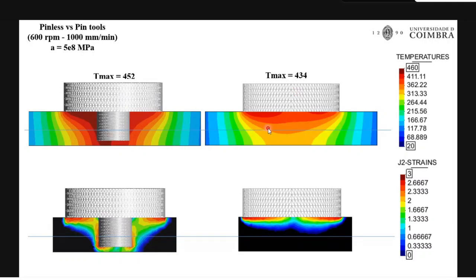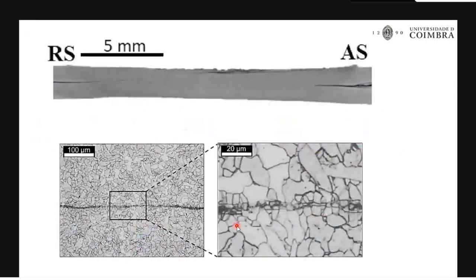Here you can find two results, the temperature and the strain. As I explained before, the advancing side has the higher temperature, and the temperature distribution is highly limited to the top region of the material, where lower temperature is shown here. When you look at the strain, you have a lot of strain in the outer boundary, because the angular velocity is higher in the outer region with respect to the distance. So you have the higher strain and higher temperature there. And here you can see that there is no strain in the lower or middle part of the joint. This can be understood by the metallographic analysis.